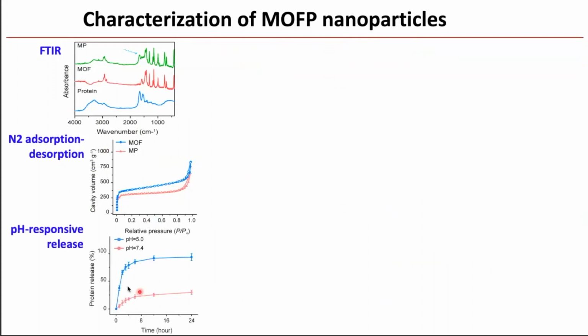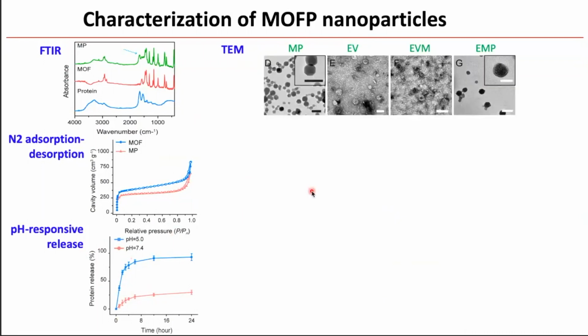We further validate its pH responsive release. At neutral pH, within 24 hours, less than 25% of the proteins are released. However, if we lower the pH to about pH 5, which is about the pH value of endosomes, you can see within several hours, the protein can be released. And then we use TEM to visualize the nanoparticles, the EVs, the EV membrane, and also the particles enclosed with EV membrane.